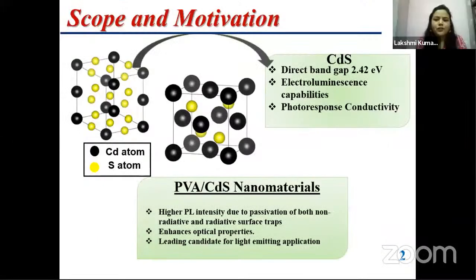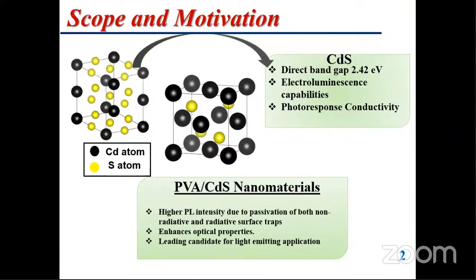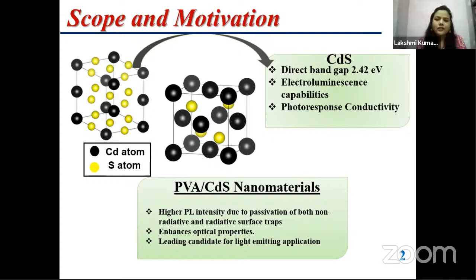Yes, sir. Actually, I wanted to suppress some intrinsic defects which are visible in CdS, the intrinsic defects present on the surface. There are so many defects: interstitial sulfur, interstitial cadmium, and vacancies of sulfur. Due to this, we cannot achieve tunability in our visible emission. And also, I wanted to achieve more visible absorption, which I have seen in my absorption spectra. So I wanted to use this ultimately in light emitting applications.